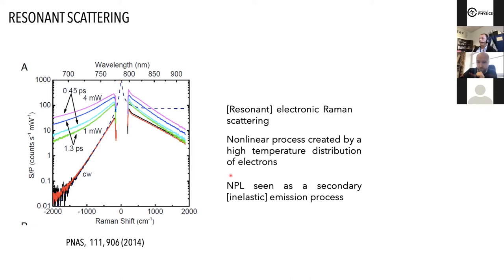Okay, and the interesting point in this study is that this nonlinear process was created by a high-temperature distribution of electrons. The hypothesis of that work, and I think this was very interesting because it started to pinpoint an effect that was known otherwise, is that following the absorption of the pulse, the nanostructure is going to be out of equilibrium, right? So you're going to have all the pulse energy absorbed by the electron subsystem. And these electrons will be brought to an elevated temperature, which is not at equilibrium with the lattice, okay?